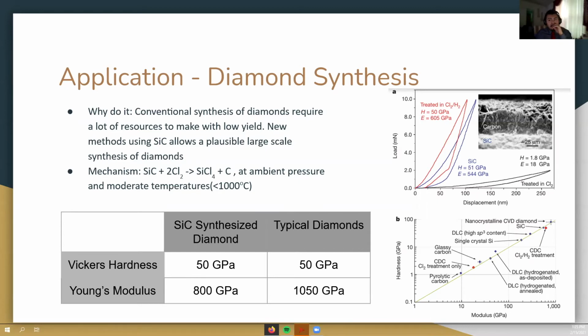And not to mention, the diamonds created using this method have very similar properties to those found in the natural world, with an identical or a tested identical Vickers hardness of 50 gigapascals and a near similar Young's modulus value.